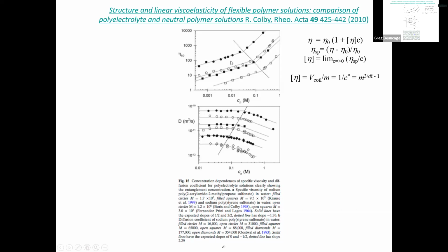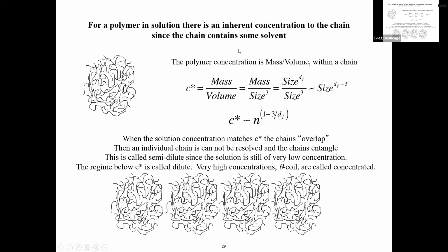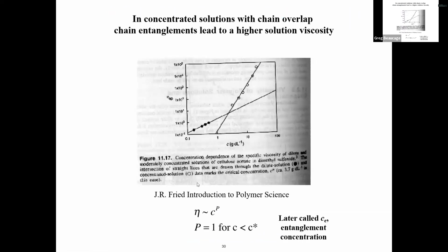Right, so you'd think that that number would be the same thing as this C star. In other words, when you saw that upturn, and originally this was kind of how people measured C star because it's easy to do. You take polystyrene, put it into like toluene, then it's like a solution, all of a sudden it becomes napalm up here, right? So then it shoots up. The napalm stuff is more viscous, it sticks to the skin.